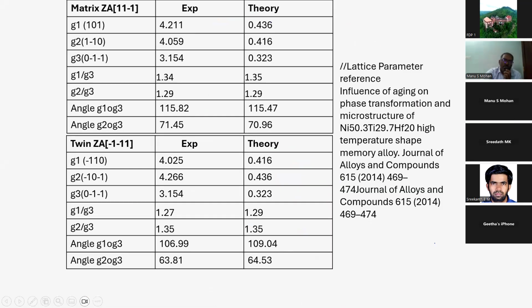Now you have to see how in X-ray you match it. You generate the pattern - a simulated pattern or Joint Committee on Powder Diffraction Standards (JCPDS) file. You compare the peak position with the intensity. You may not match because in metals it's very difficult to match due to texture. When you roll it, forge it, or subject it to metal forming operations, the intensity will change. You cannot compare it easily - advanced software is required.